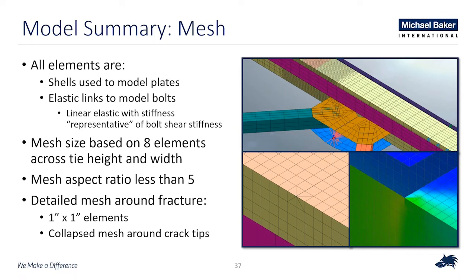And then around the fracture location, the mesh density was increased to about 1 inch by 1 inch elements, and at the corners of the cracks, we did a procedure that is typically used when doing more fracture-oriented analysis. This is an approximation, but we collapse the mesh around the crack tips. This helps with integration, and if you were to do a mesh sensitivity analysis where you halve or double the mesh, this sort of procedure helps you with convergence around those areas. At the crack tip, you won't get convergence, but within an element, you typically get pretty good results. You can go to the next one.